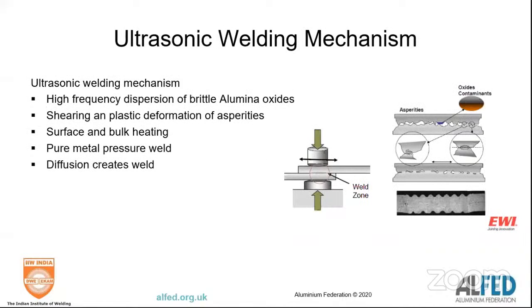Because alumina is brittle, ultrasonic frequencies actually shatter and disperse alumina. And then pure aluminium to aluminium is a shearing thing, so you form surface and bulk heating, and it becomes a pressure weld. So ultrasonic welding deals with alumina. In essence, it's a micro explosive weld. Lots of work going on, and Ford has now started to commercialize the process. If you're talking microelectronics and small components, ultrasonics is catching on in the UK as an alternative to soldering.